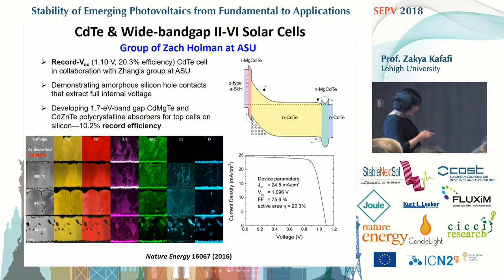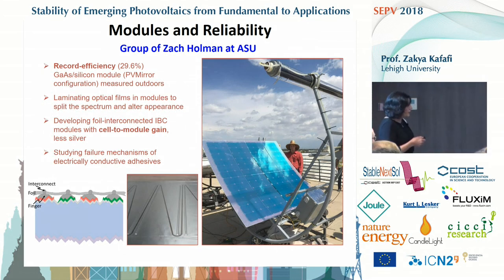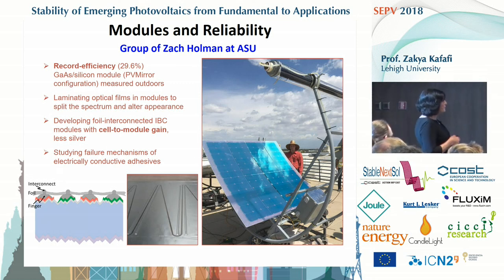In collaboration with another group at Arizona State University, Zhang's group, they got a very efficient CdTe cell with very high open circuit voltage. They also demonstrated that amorphous silicon hole contact can extract full internal voltage. He developed another type of cell, which is a cadmium magnesium telluride with a band gap of 1.7 eV, and also another polycrystalline absorber, where he replaced the magnesium with zinc, achieving a record 10% power conversion efficiency. He has also done a fairly efficient module based on gallium arsenide on silicon and measured their efficiencies outdoors.